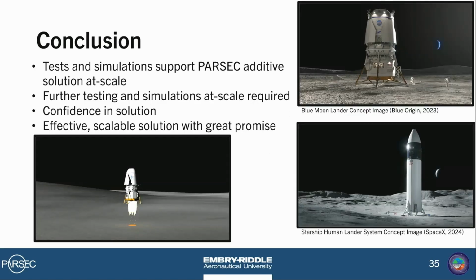For conclusion, we have found that through our PSI reduction effort that we have researched over the past year, we have tested a solution of a granular additive to be deployed onto a lunar lander and thus on the surface below. This would bind and conglomerate regolith particles. For the last year, our data gathered has culminated in our testing campaign, final budget estimate, analysis, and VNV. And all of these have pointed to an attainable, realistic solution for HLS that would turn a plume of typical destruction of the surface to one of exploration by mitigating PSI and creating a rough landing pad.